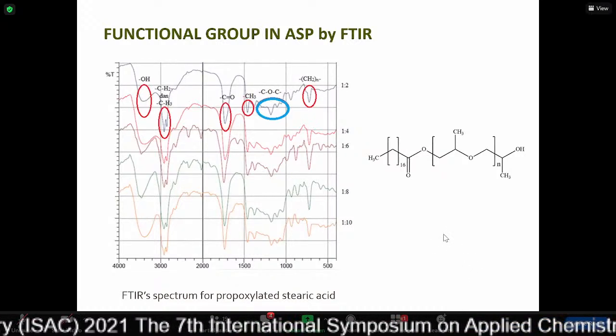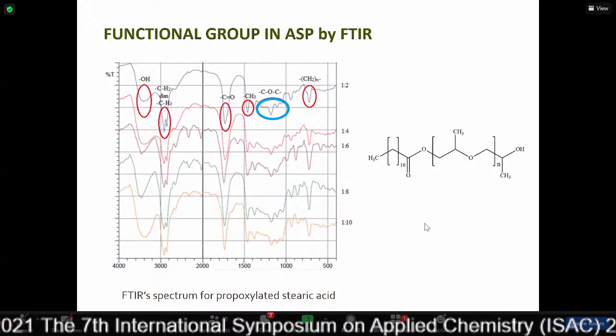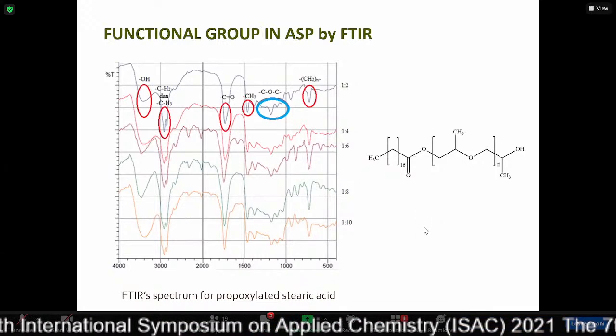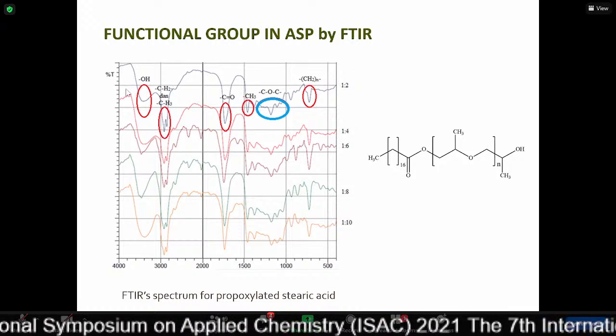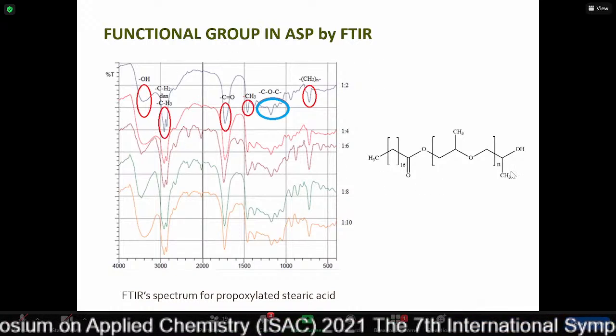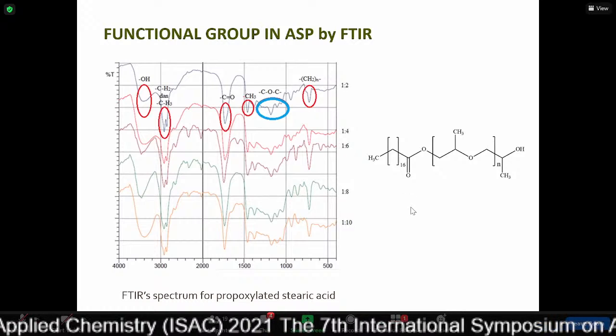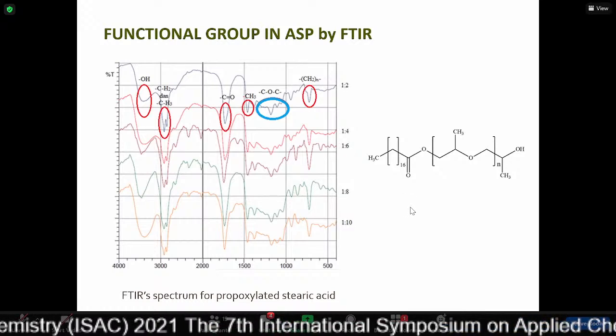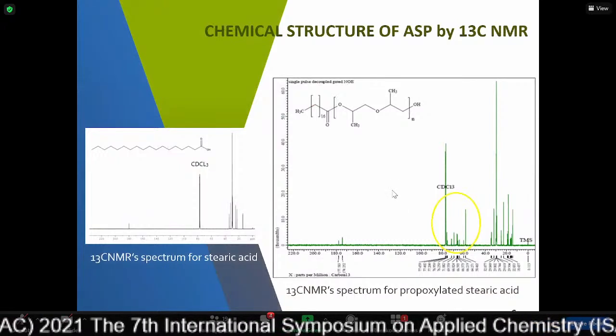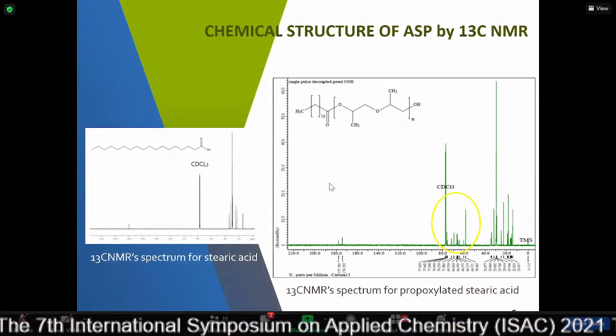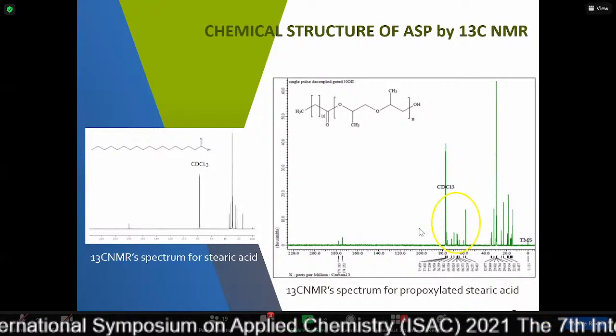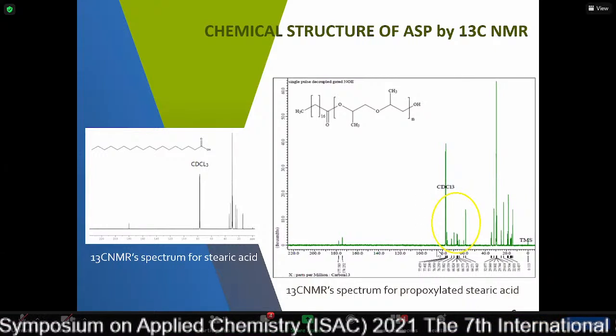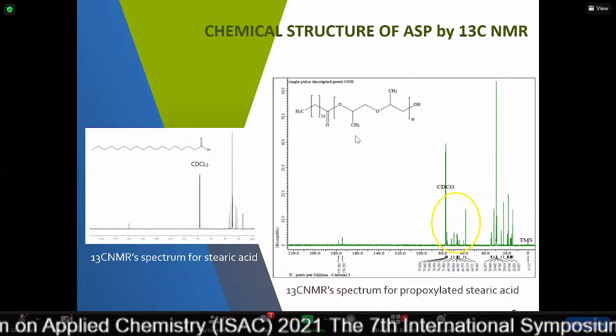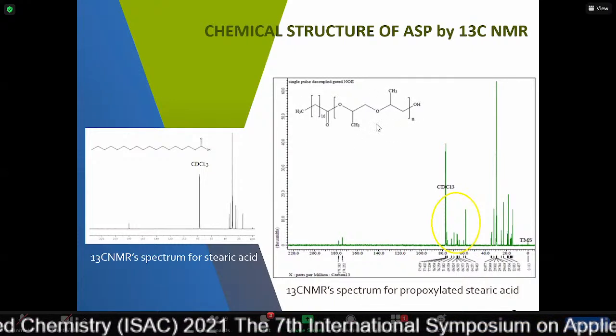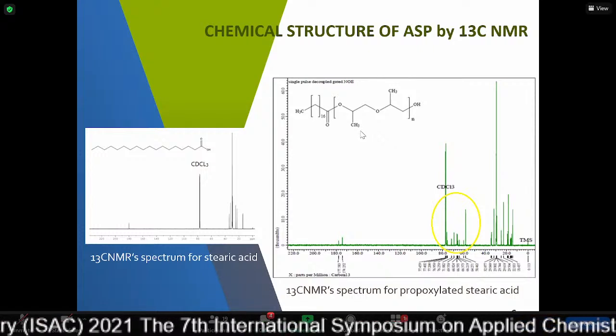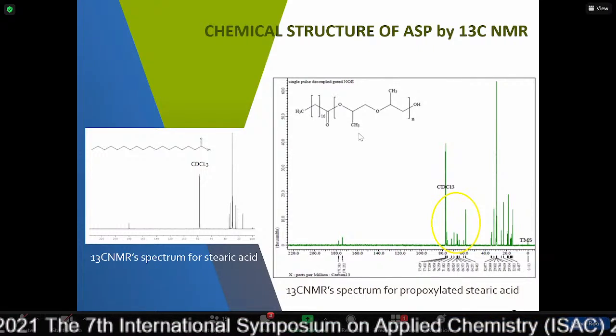This is the result of the functional group, the wavelength values from the FTIR. It shows the functional groups in the molecular structure of stearic acid propoxylation. This is also the characterization from the NMR. We can see in this yellow part, it indicates that the polymeric surfactant stearic acid propoxylation has occurred in this reaction in this work.